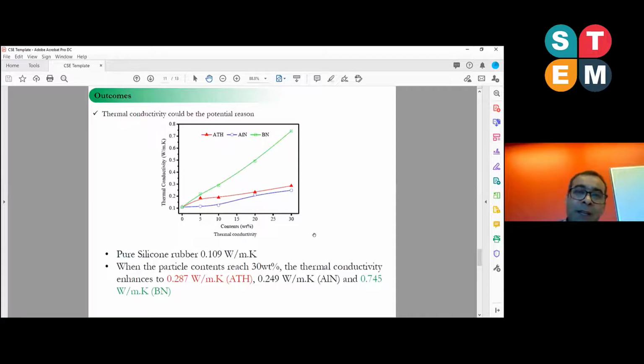So why is this happening? Why are the ATH and especially the BN, boron nitride, performing so well? The reason is that we measured experimentally the thermal conductivity of each sample. Thermal conductivity increases linearly with the addition, but most with the BN, because BN is an inert, inorganic filler that can increase the thermal conductivity of the insulation, and at the same time it can retain good electrical insulation properties as well. So from 5 to 30 weight percentage of the BN